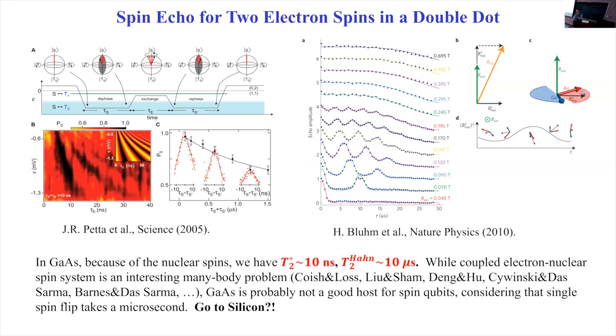I think one of the other reasons was people also recognizing that you don't really need that high mobility for making good quality quantum dots, right? For the quantum Hall effect, what you do is you dope those gallium arsenide structures heavily to give you a large enough number of electrons in the 2D electron gas. And the presence of that large 2D electron gas would actually screen out all the disorder from the dopants, right? By modulation doping, you screen them out. It's like, at high tide, all the rocks on the seashore, you don't see them. They're all underwater. But we're working with quantum dots. We want to have one electron per quantum dot or a few electrons per quantum dot. So we're going to deplete the whole system down.